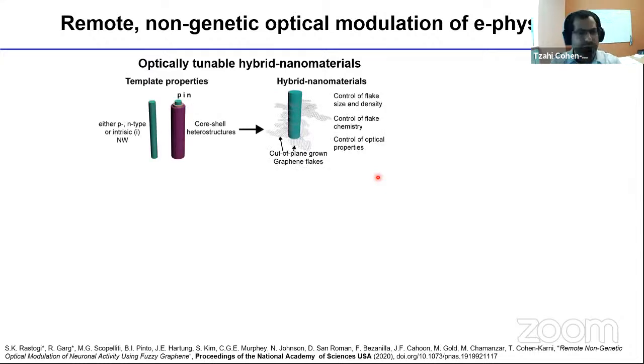Let me show you how we are doing it. We are generating a library of optically tunable materials. We call it hybrid material because we are using silicon as the template, and then we grow a shell of graphene, as I mentioned before. And this graphene shell, we can control the density, the size, and actually the chemistry of these graphene flakes as well. We can also control the nature of this core.